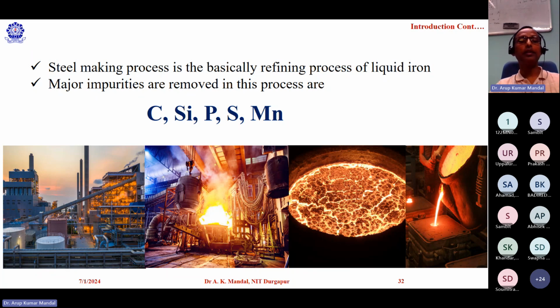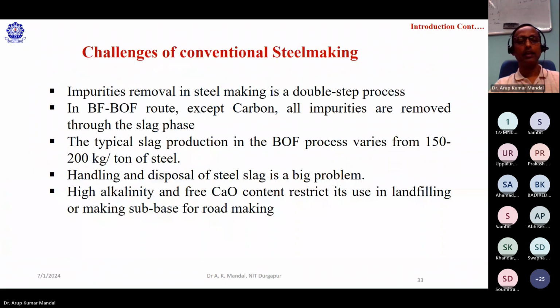Then the major impurities to remove are carbon, silicon, phosphorus, sulfur, and manganese. You can see the carbon can easily react with the oxygen even at lower temperature. Silicon also can be oxidized with the oxygen at the steelmaking temperature, it can easily react. Similarly, phosphorus and manganese can also react to form oxides, but sulfur has some difficulties. Sulfur, when dissolved in the metal, will not react easily.